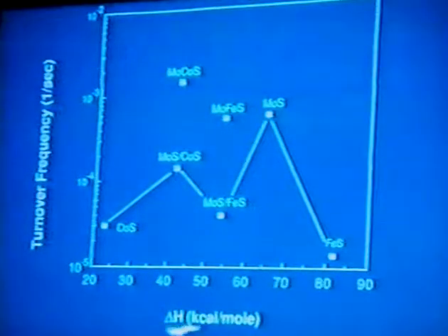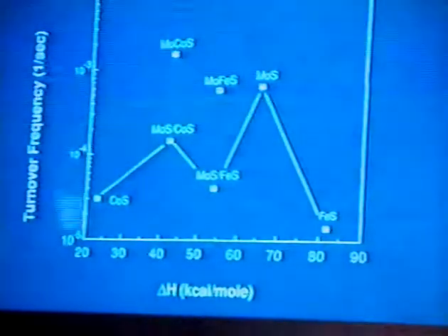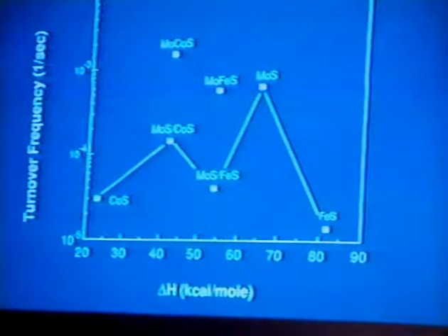If we think about what this is telling us, the strength of the bond of sulfur to the metal site has a very significant effect on the resulting activity. We typically call this a volcano plot if we had connected the points for the monometallic and the bimetallic system. This is for the alumina supported series.